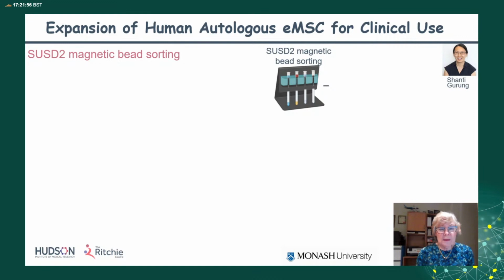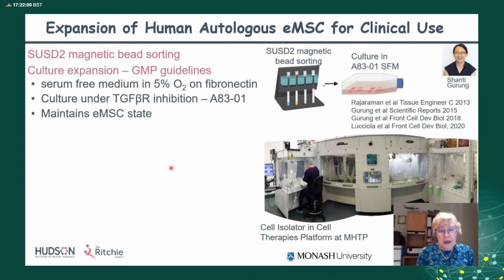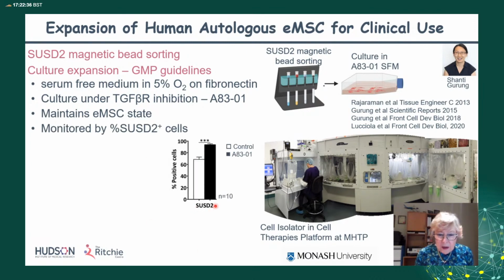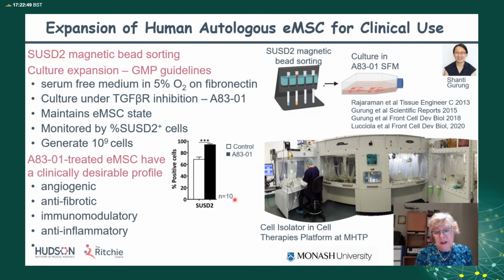Now, because they're not common cells, we need to expand them in culture. And the way we've been doing that is we use our SUSD2 marker to pull the cells out of single cell suspensions by magnetic bead sorting. We then are developing SOPs using GMP guidelines, and where we're at now is we're using a serum-free medium, low oxygen concentration on fibronectin matrix. We're using a small molecule inhibitor, A8301, of the TGF-beta receptor to keep them in the EMSC undifferentiated state. And you can see that here in the figure that A8301 treated cells are 90 to 95% SUSD2 positive, really important when you're using autologous cells for quality assurance. We can generate large numbers of cells, and they have a very desirable, clinically desirable gene expression profile of the kind of healing properties that you would want.